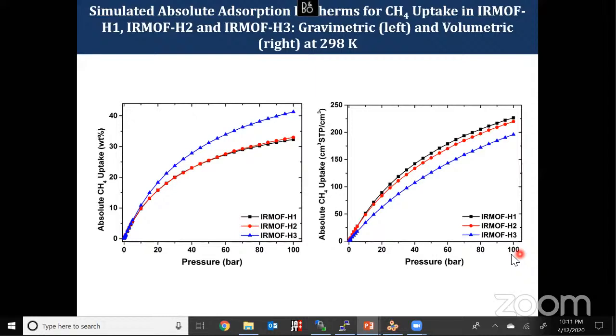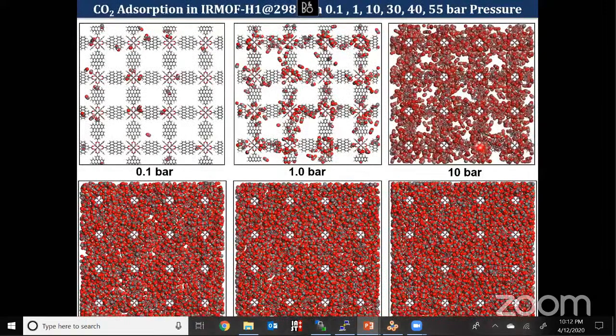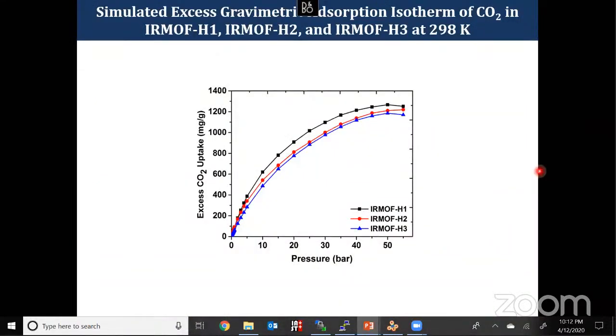I ran the simulation for up to 100 bar. So there is not much adsorption of methane, and this is for CO2. So we ran the simulation for 50 bar, and here we got IRMOF-H1 showing higher uptake than the other two MOFs. So we can use this IRMOF-H1 for CO2 capture as well as hydrogen purification. So that's what we got from this simulation result.